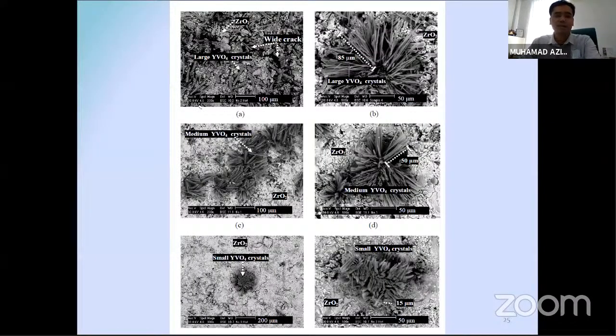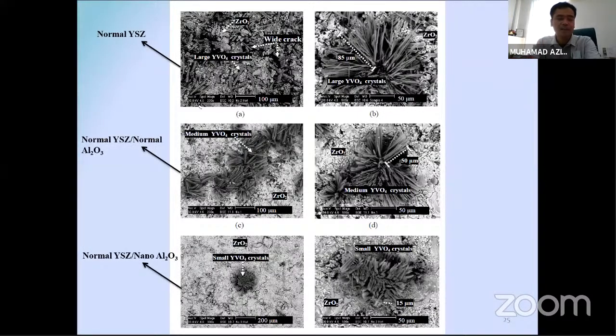So this is what we can observe if you're talking about spall samples. This is the normal YSZ only, then YSZ with alumina, and this is with the nano alumina coating. What we observe is that this almost covers the entire surface, meaning the structure is very porous, and then the corrosive salt can easily penetrate. But if you have another layer, at least you can reduce it. Based on our calculation, from the image analysis, around 45% of the area is covered by YVO4. But if you have a nano alumina, you can further reduce to only 20% cover.